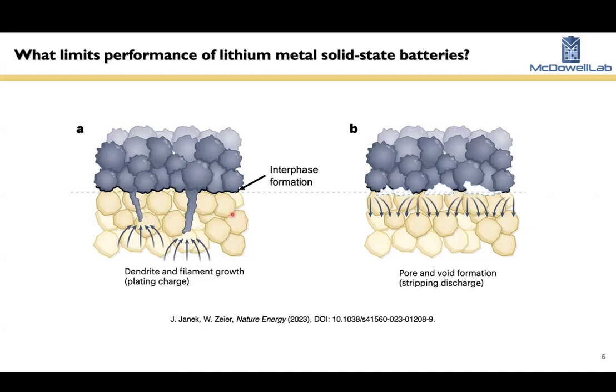The first thing is the fact that lithium grows dendritically or in a filamentary fashion through solid electrolyte materials. So even though lithium is very soft and has a low yield strength, it can penetrate very high stiffness ceramics, it can penetrate polymers, and it grows through these materials to short circuit the cell, which kills your cell. Bad situation. So this is a major problem.